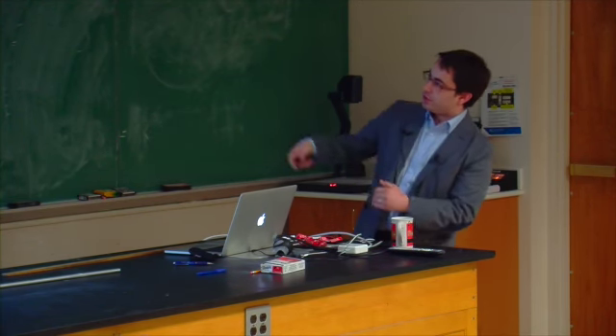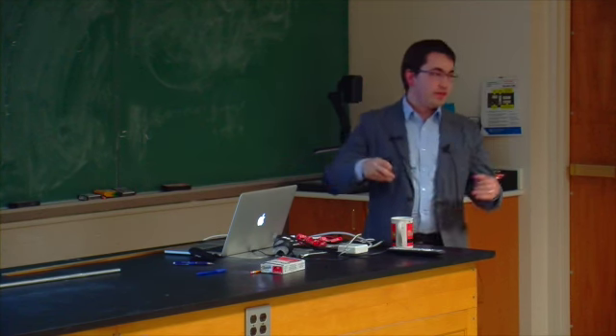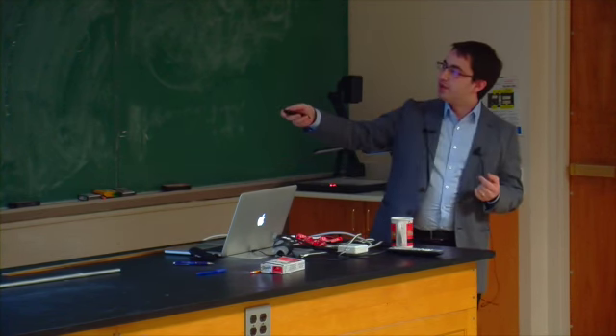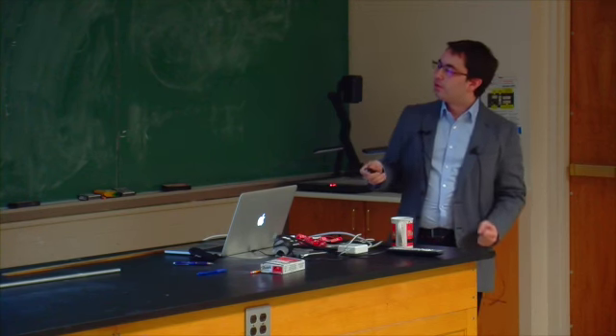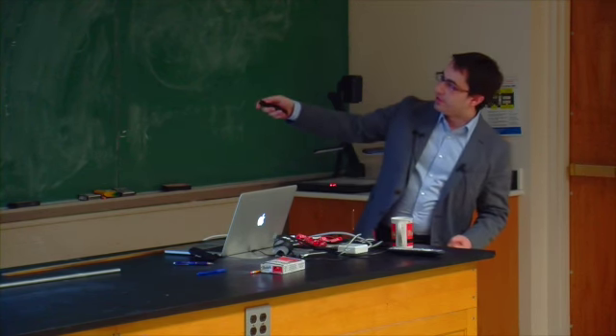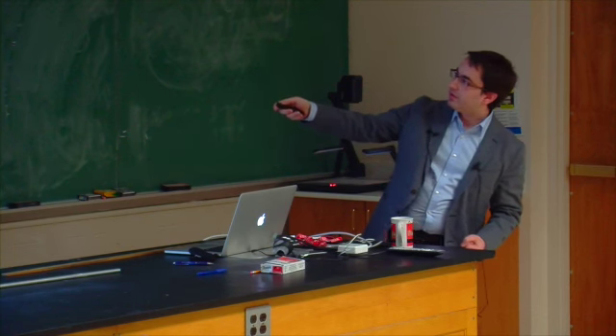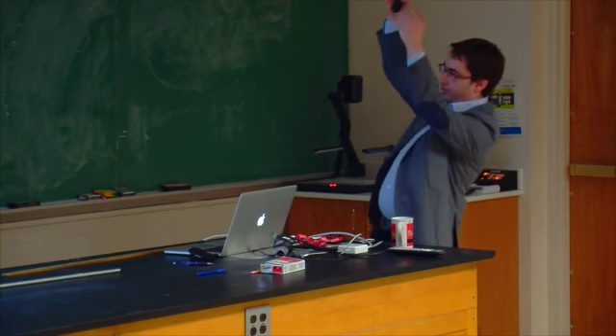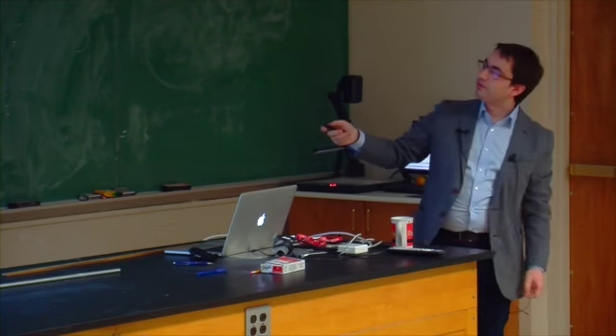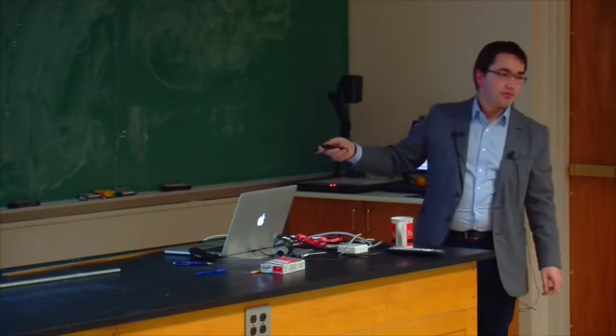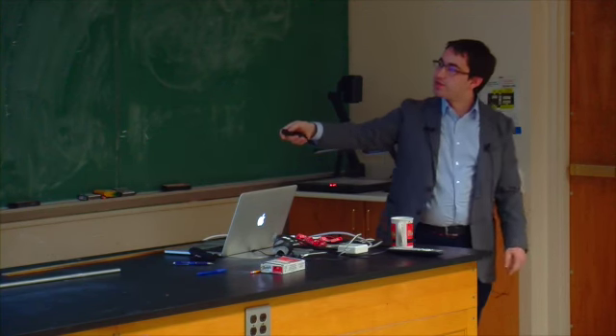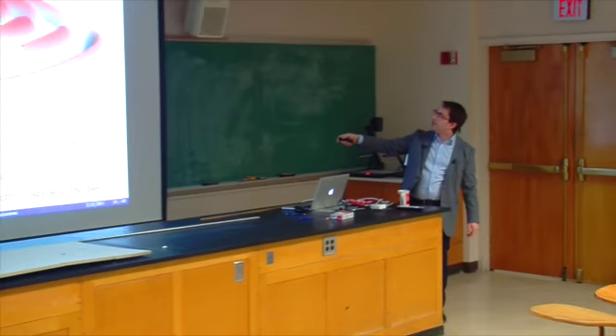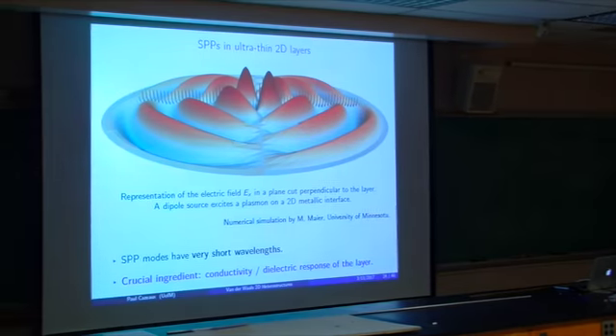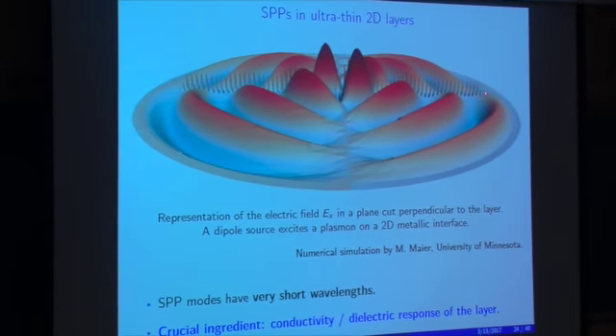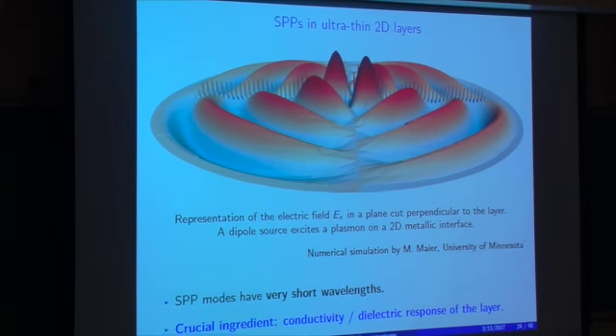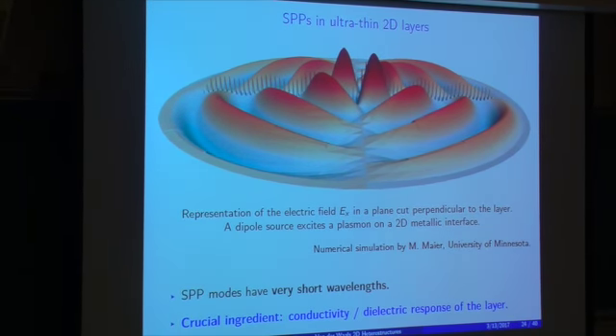So it's a finite element simulation. We represent the electrical field in such a plasmon, which is excited by a small dipole position just above the layer. So here the layer is represented by a line, which is like this, coming out of the plane. We see the rest of the wave, the electromagnetic wave, going through space, absorbed by absorbing boundary conditions on the sides of the simulation domain. And then on the interface, we can observe the plasmon with very high oscillations of the electrical field.